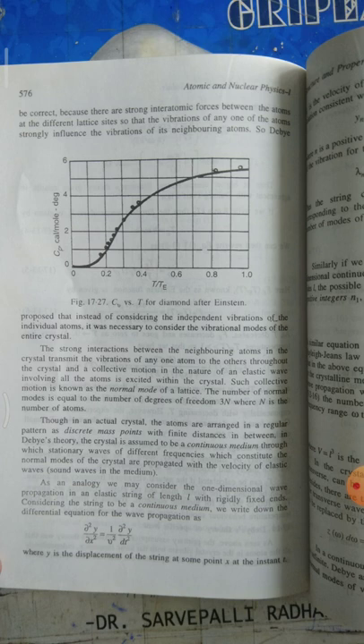Thus, in an actual crystal, the atoms are arranged in a regular pattern as discrete mass points with finite distance in between. In Debye's theory, the crystal is assumed to be a continuous medium through which stationary waves of different frequencies, which constitute the normal modes of the crystal, are propagated with the velocity of elastic waves, sound waves, in the medium. As an analogy, we may consider the one-dimensional wave propagation in an elastic string of length L with rigidly fixed ends, considering the string to be a continuous medium.